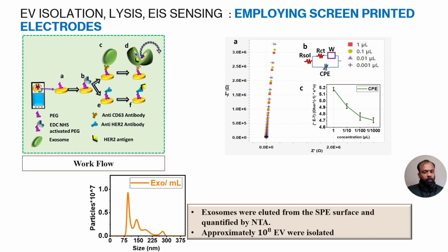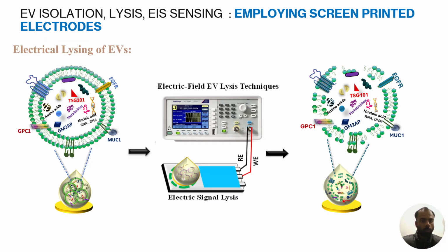The techniques established on silicon wafer platform were extended to screen printed electrode, and we found that approximately 10^8 extracellular vesicles can be isolated. Once the extracellular vesicles are immobilized on the screen printed electrode, a voltage is applied to the electrode for lysing the extracellular vesicles, making this technique suitable for microfluidic platforms to implement a detergent-free lysing technique.